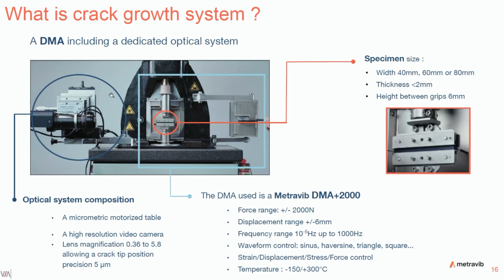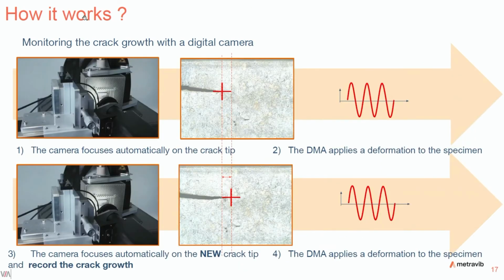etc. And we use a dedicated optical system composed of a micrometric motorized table, a high resolution camera, and a lens magnification, allowing us to follow the crack tip with a precision of up to 5 microns. So how does it work? First, the camera can focus automatically on the crack tip. You have an example just here. Just after, the DMA can apply a deformation to the specimen, for instance a sinus signal. Then the camera can focus automatically on the new crack tip, and once again the DMA applies a deformation and records the crack growth. So the system is quite simple.